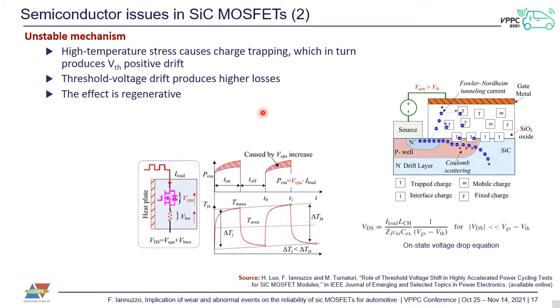What happens? What happens is relatively well known. It is called a charge trapping mechanism. If we focus on this picture here, where you can see a schematic cross-section of an elementary cell of a MOSFET, in this case a silicon carbide MOSFET, what happens is that at extreme conditions, for example high junction temperature and high current density, there is a non-zero probability that a hot electron finds its way towards a gate electrode, which is positively charged, and along this way can remain trapped inside the gate oxide.